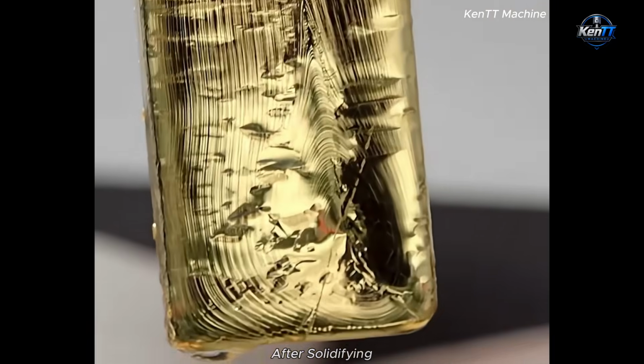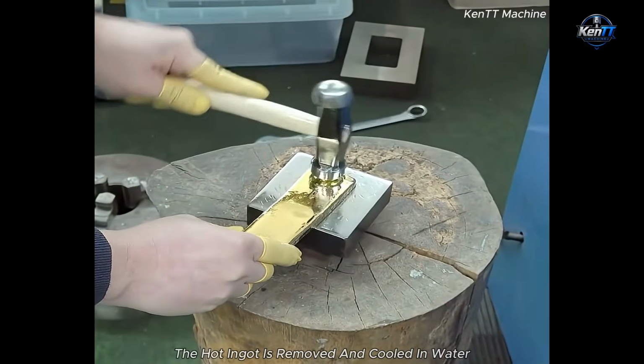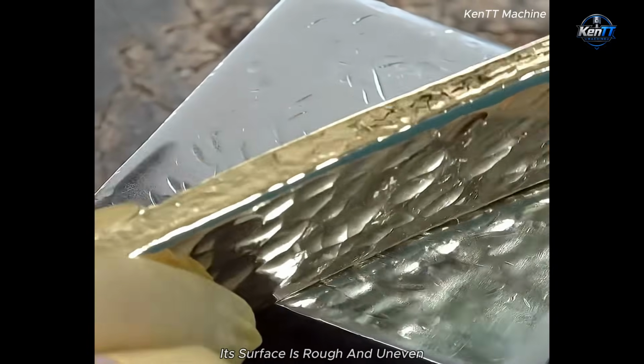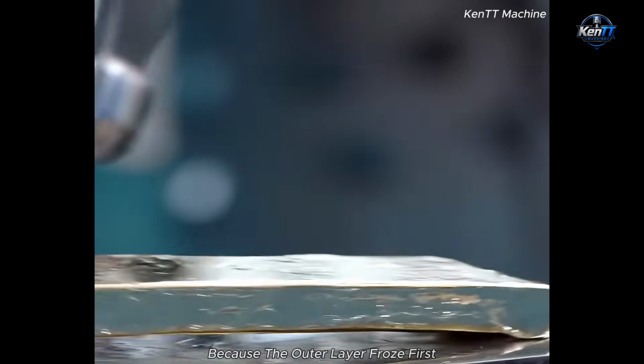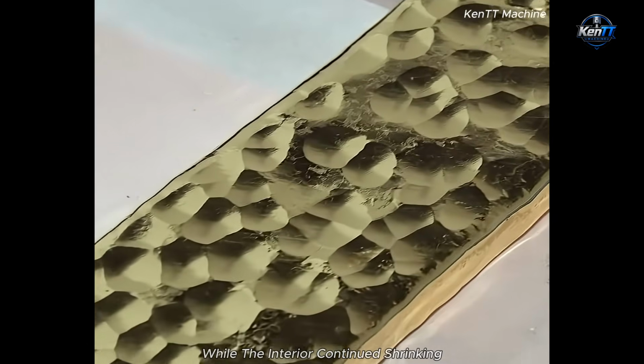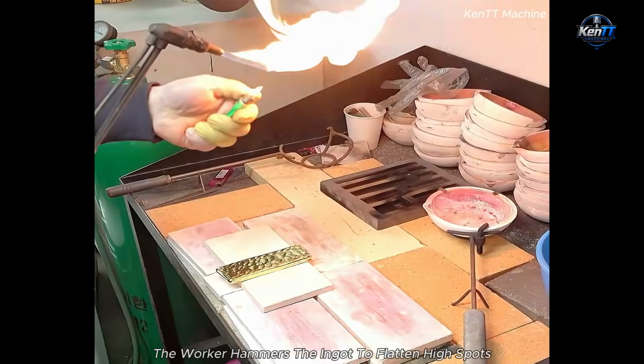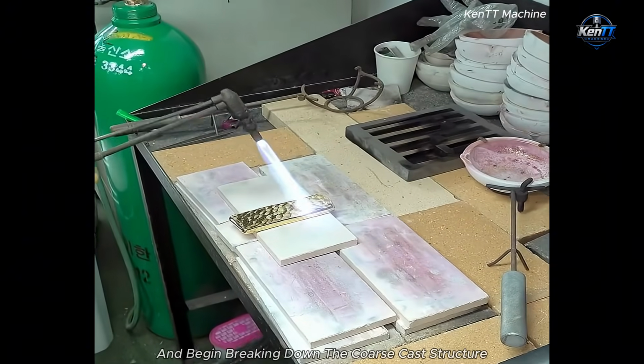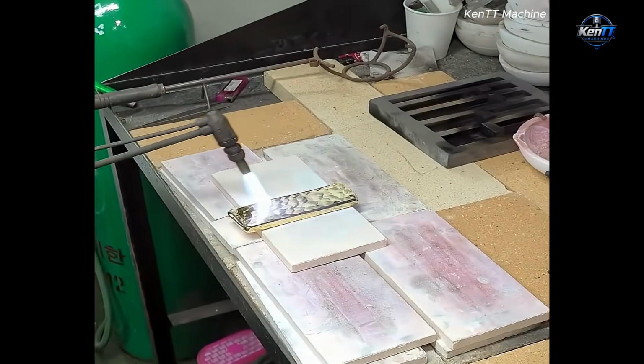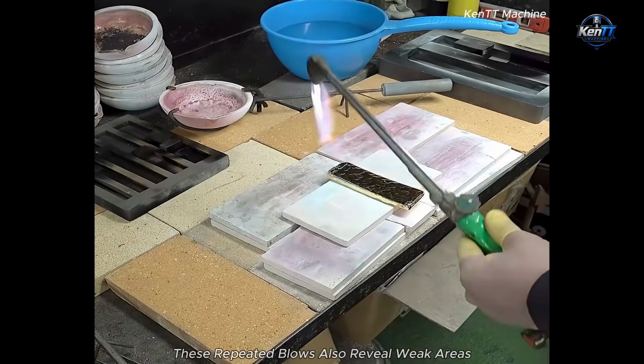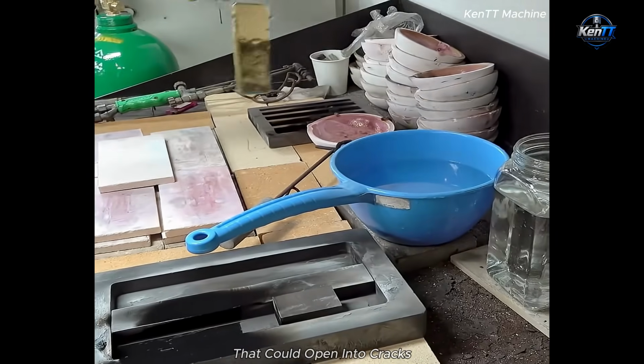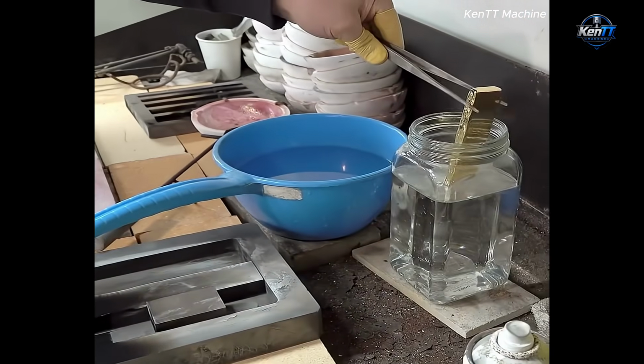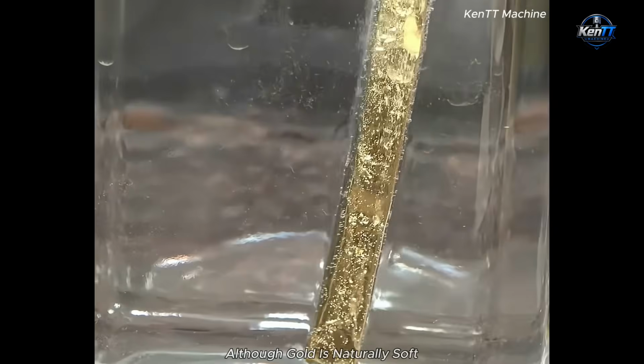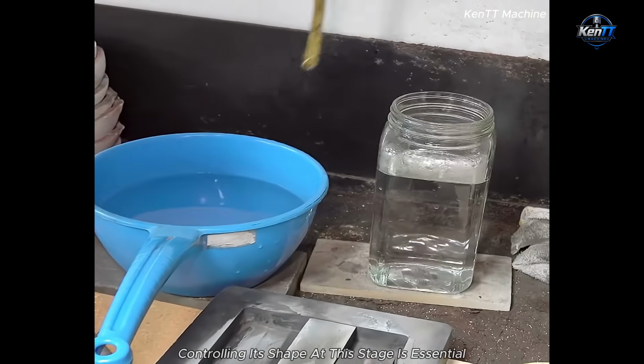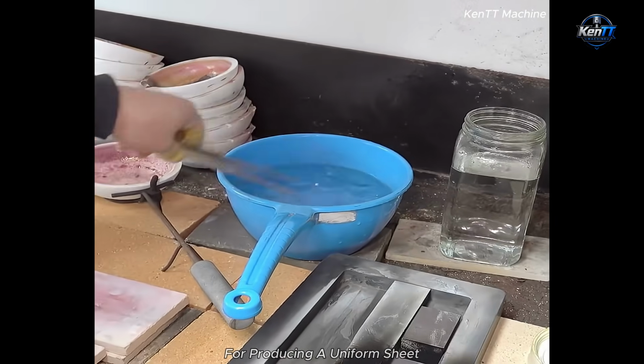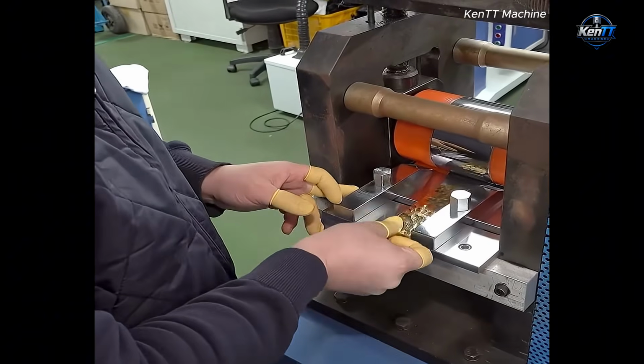After solidifying, the hot ingot is removed and cooled in water. Its surface is rough and uneven because the outer layer froze first while the interior continued shrinking. The worker hammers the ingot to flatten high spots and begin breaking down the coarse cast structure. These repeated blows also reveal weak areas that could open into cracks during rolling. Although gold is naturally soft, controlling its shape at this stage is essential for producing a uniform sheet.